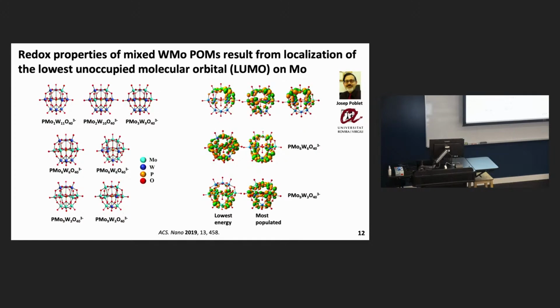So one of the nice things about a technique like ion soft landing is the material that you've made is extremely well defined. It's not a mixture of a bunch of random things that you don't know what they are. And because of that, it's easier to characterize experimentally, but also easier to model theoretically. And we were very fortunate to collaborate with Joseph Poblet, who's been working on these systems for years. And he went through and used density functional theory to calculate all of the different ground state geometries of these various ions, which are shown on the left. And then he calculated the electronic structure, specifically the lowest unoccupied molecular orbital, as shown on the right-hand side.